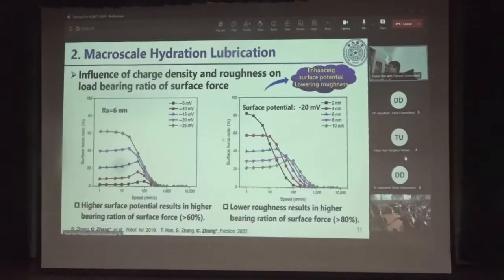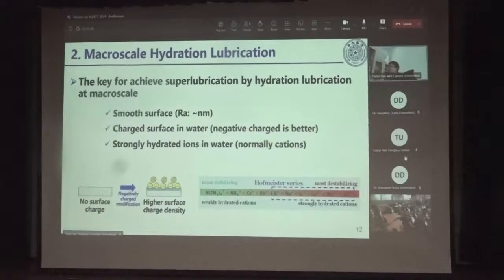So from the calculation, we know it is possible to decrease the friction by hydration effect, especially in the mixed lubrication region, because the surface force can support most part of the applied load. So from the calculation, we know if we want to get superlubricity, there are 3 key factors. We need to satisfy these 3 factors. First, the surface should be very smooth, and the roughness should be in the scale of nanometer. And second is the surface should be charged in water, and negatively charged surface is better. And third is we need strongly hydrated ions in the water, because we need this hydration layer.